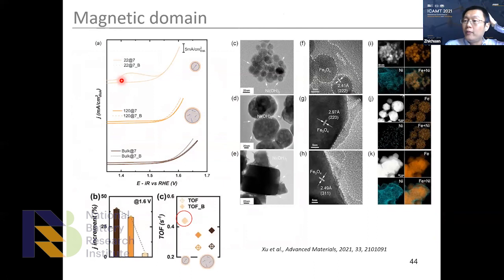And then we look at the domain effect. And this is even more interesting, because if we employ the nanoparticles, which are single domain, we will not be able to see any increment under the magnetic field, or let's say the magnetization, because no more magnetization can happen, because there are no more spin alignment over here through the magnetic domain change, right?